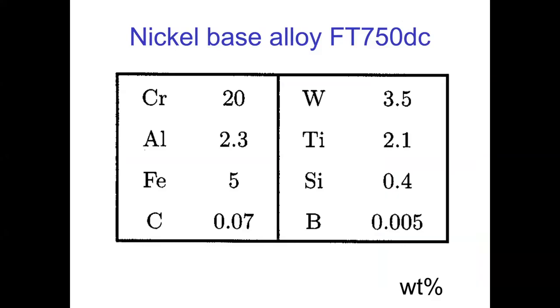And you could make it in large quantities, right? And fabricate it, etc. And if you look over here, it contains 5% of iron. Iron is not a good thing in nickel-based superalloys, but by allowing it to be there, you can use scrap material to make this alloy. Similarly, when you make a very large component, the problems of chemical segregation become much more prominent. So we used methods of kinetics and thermodynamics to ensure that if there is chemical segregation, it could be more or less homogenized during the fabrication procedure.